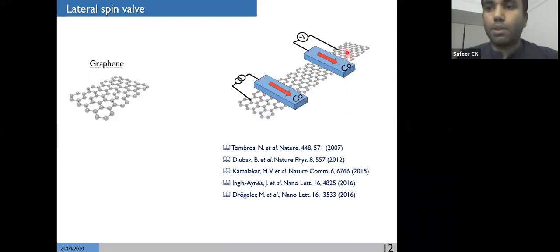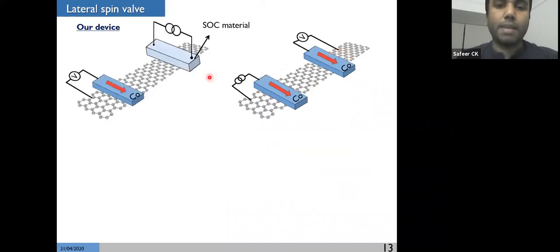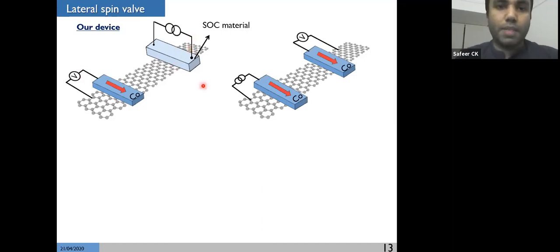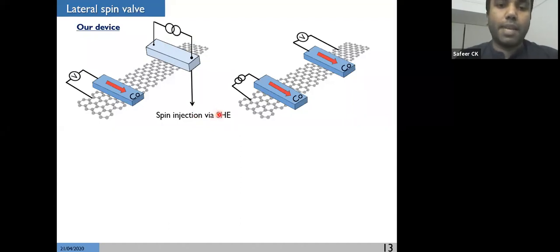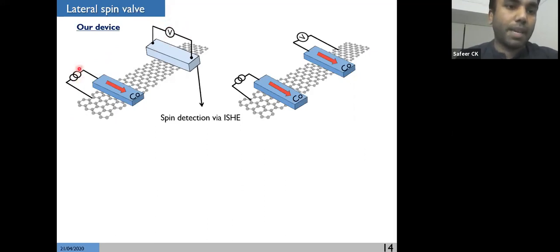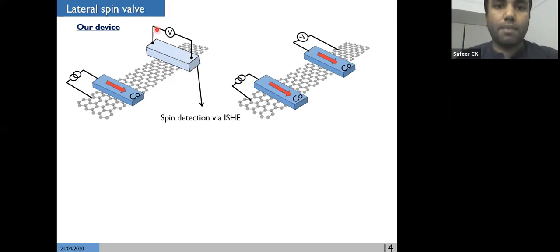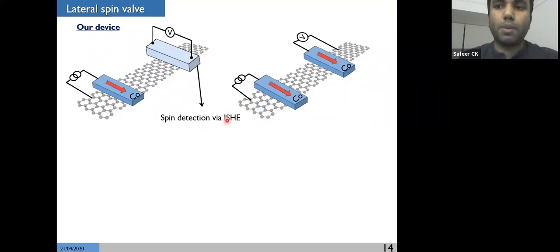What I want to do is introduce spin orbit effects into the system. The device I'm going to use is slightly different: I keep one ferromagnet for spin injection or detection, and replace one electrode with a spin orbit coupling material. If that material has spin Hall effect, it can inject spin current into graphene, which can be detected by the ferromagnet as a voltage. I can also do the reciprocal effect by exchanging current and voltage terminals — the inverse spin Hall effect. In my future slides I will show only the inverse spin Hall effect experiment because it is easier to explain.